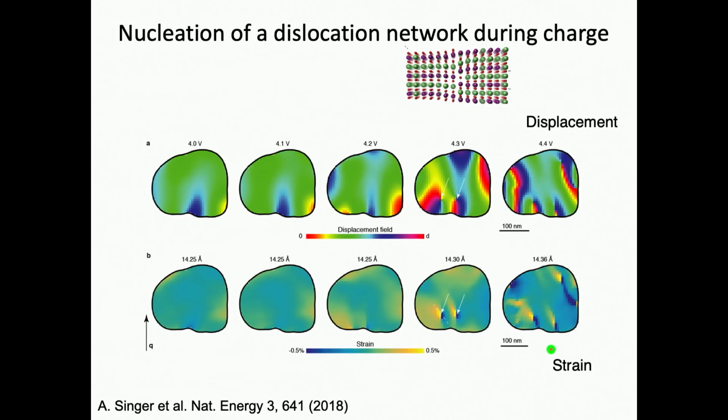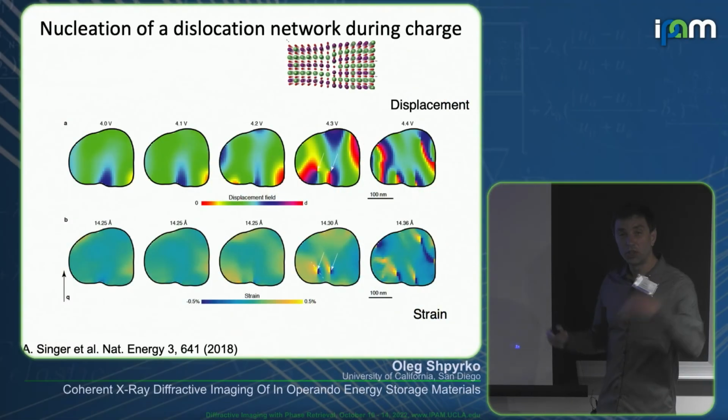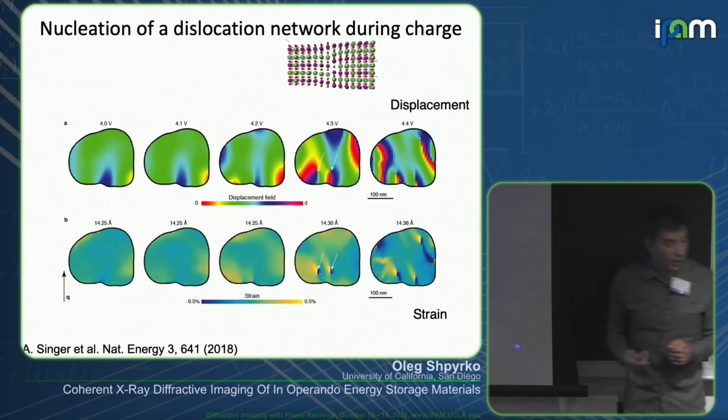And again, now you can see these pinch points as these regions here that give you this phase wrap, this kind of butterfly-type pattern of strain around them. And there are more of them as you go to the high voltage. So we believe, right, correlation is not causation, but we know that this material deteriorates as we introduce more and more of these defects.